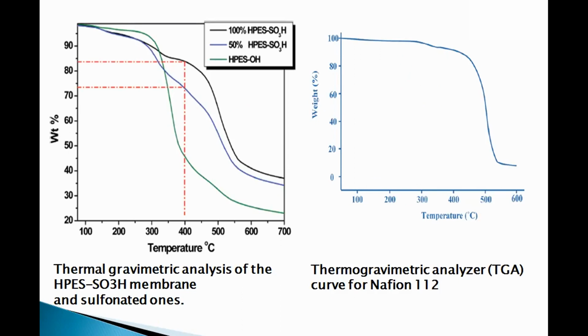We conducted the thermogravimetric analysis of the composite membrane. As we can see from the TGA, the Nafion is stable until about 400 degrees. There is no degradation. For our 100% composite membrane, we lost about 13%. For the second membrane, 50%, we lost about 27%. But this is the temperature. We run the fuel cell at about 100 degrees.